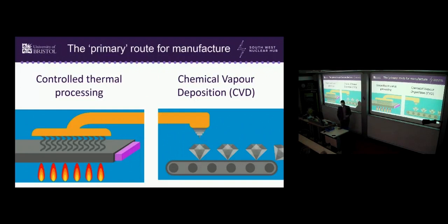So there are actually three ways you can make a diamond power cell betavoltaic. The first way is controlled processing of the graphite to release a gas, and you turn that gas into methane. And from that methane, you mix it with hydrogen. This is why we'll be talking later, Tim. And you grow the diamond by a process called chemical vapor deposition. But essentially, you spark a plasma. Typically, we either use very hot filaments or we use a microwave. And in that hydrogen plasma, it causes the methane to break up and for the diamond to be deposited down